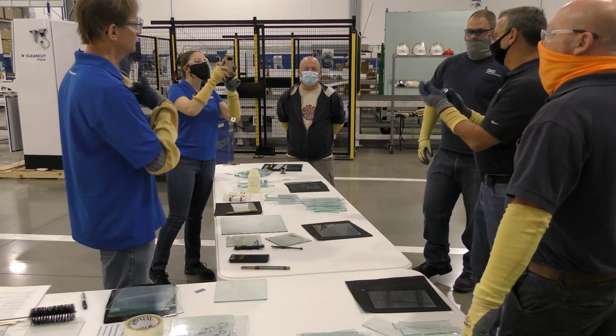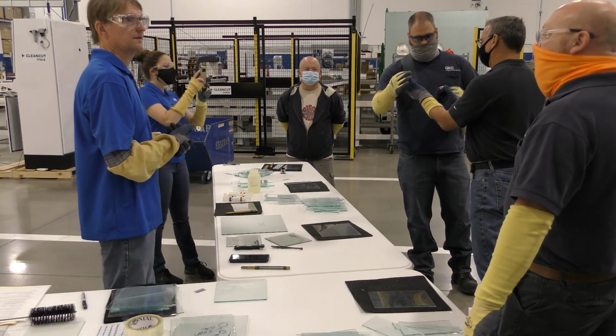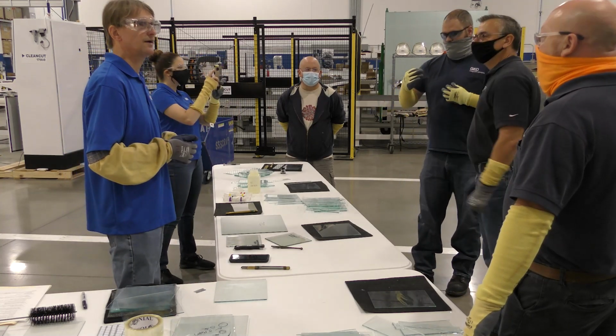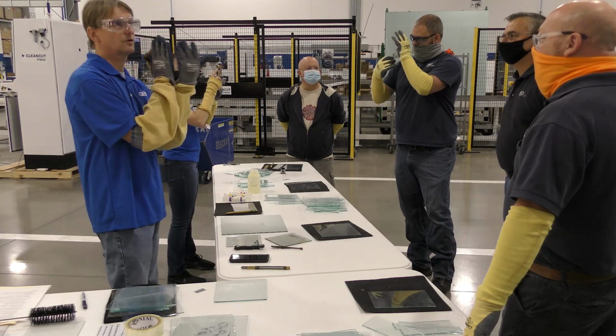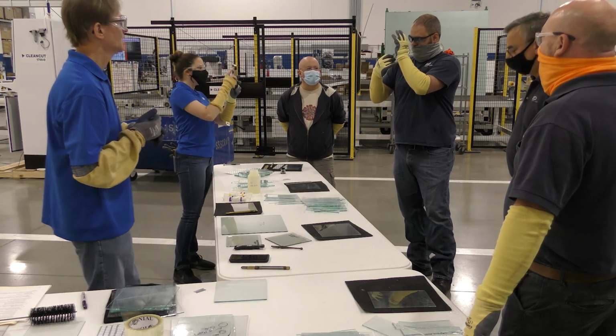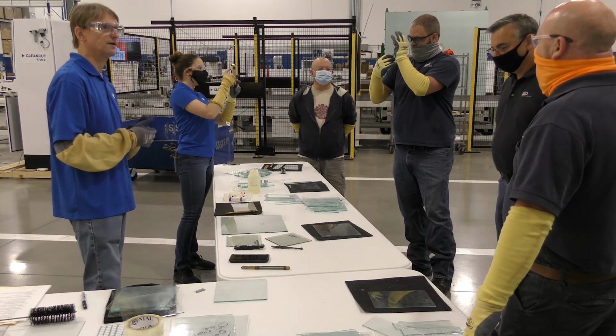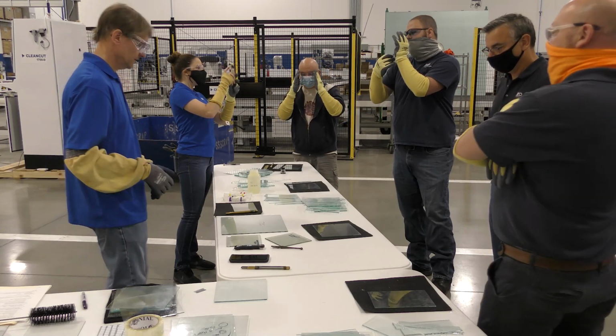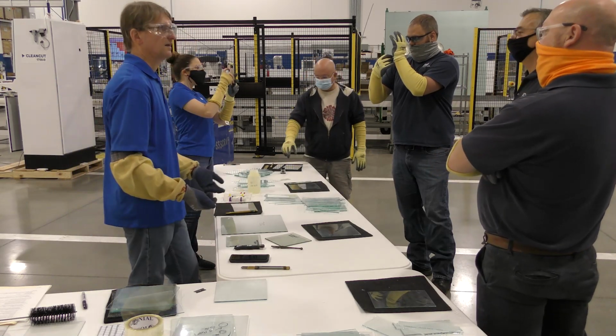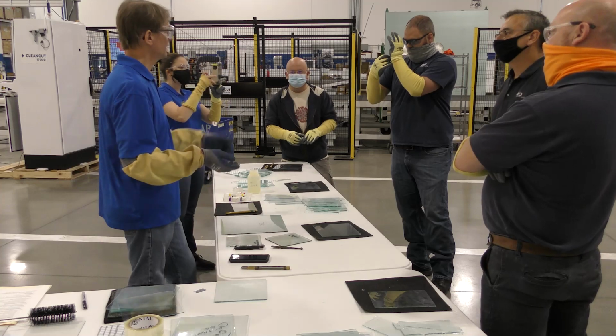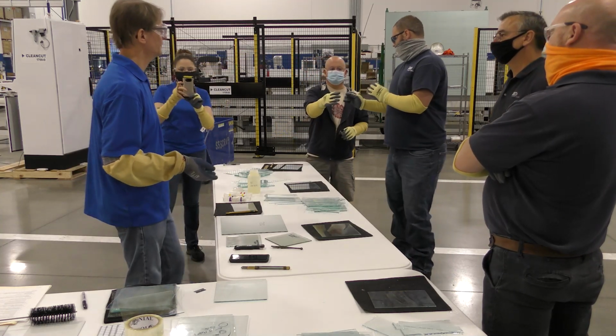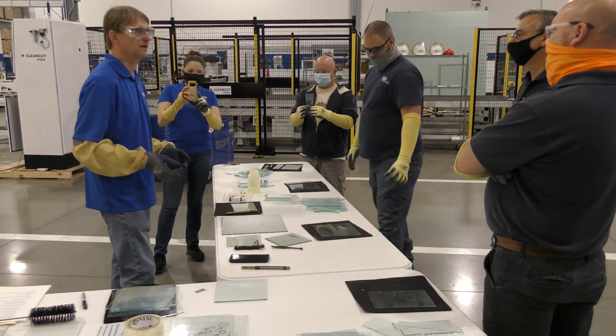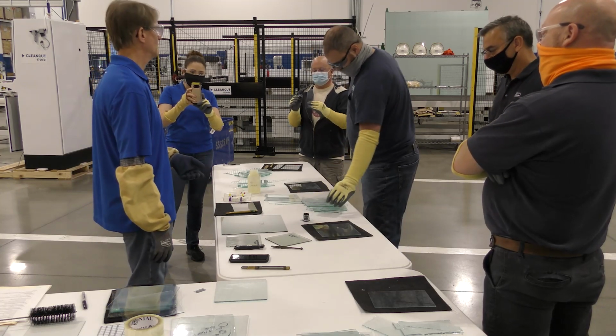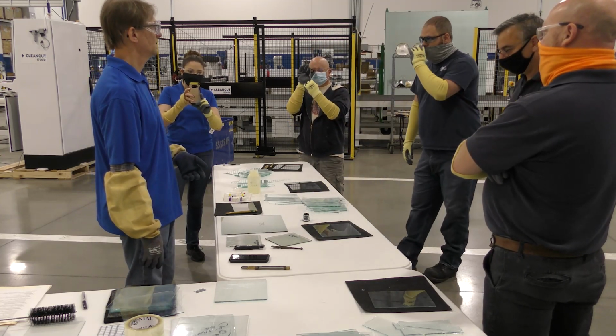This is something you can't do on a machine. You can't check that, but you could definitely look at the edge on an optical comparator with the jeweler to get a good idea of how deep you're penetrating. And force-wise, for this single strength glass, if you're more than like 8 pounds or 6 pounds, you're pushing too hard. You're using the wrong wheel or you're pushing too hard.